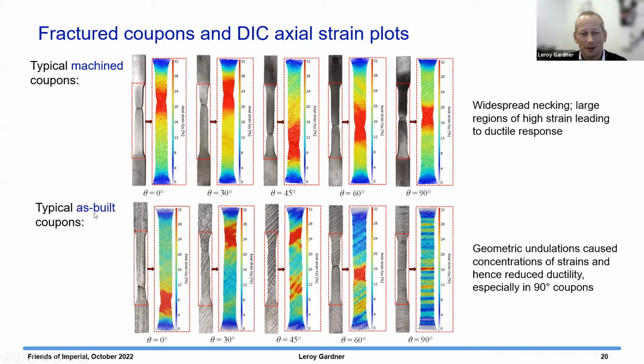But when you look at the as-built material, it's still true that you've got widespread zones for the lower angles. But when you get up to 90 degrees, you can see it's very much more concentrated. All of the deformations running into that minimum cross-section, and that has a negative effect on ductility. And what we also found is that, as you'd expect, print quality is important, and the technology is still evolving, and print quality is getting better. And of course, the better you can print it, the lower the surface roughness, the less this sort of localization issue becomes important.